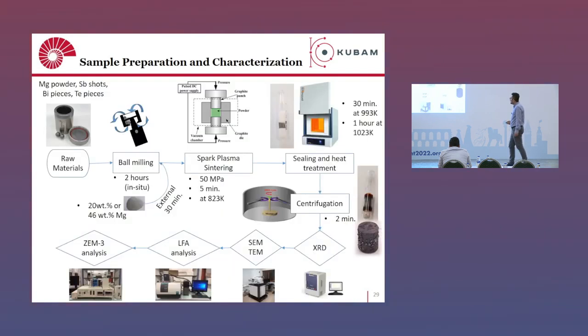Let me explain it to you here. You can put all these materials in a steel vial and do high energy ball milling, let's say 2 hours of high energy ball milling. If you add the magnesium at the very beginning, this is in situ. If you add the external magnesium after the 2 hours of ball milling, this is called the ex situ preparation. So this will lead to powder material.